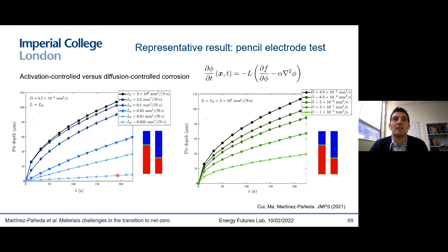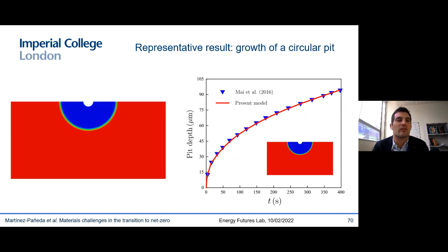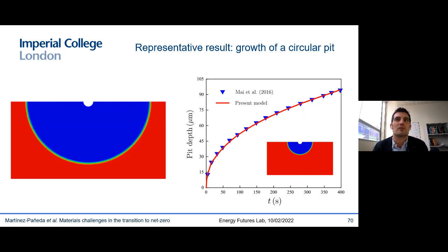But as we increase the mobility coefficient, we move into the parabolic behavior, indicative of diffusion control corrosion, with electrochemical reaction at the metal electrolyte interface occurring very fast and leading to the saturation of the surface concentration of metal ions. And the right shows how the corrosion becomes faster with larger diffusion coefficient for a diffusion control process, as you would expect. Here you can see the case of a semicircular pit growing uniformly, and you can see that we get a good agreement with other numerical estimations.